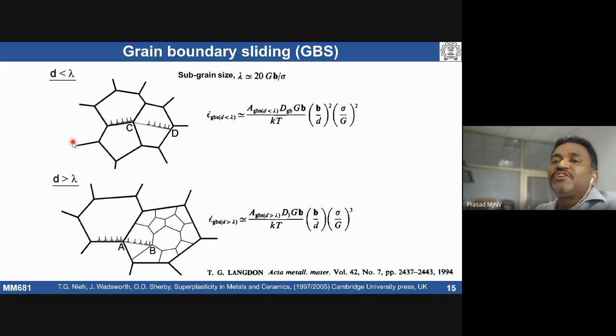Here are the constitutive equations which describe it. Typically in superplastic materials, grain boundary sliding is going to be observed in fine grain size materials. The grain size will be finer than what we can talk about as the subgrain size of a particular material. So in that case, most of the time people use this constitutive equation for superplastic grain boundary sliding. In the bottom case, grain boundary sliding in coarse grain materials, it's not necessarily superplastic, because we know we need some minimum grain size to see superplasticity. So these materials might not exhibit superplasticity.